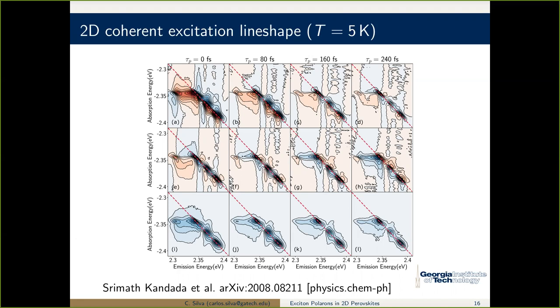It's excitation-induced dephasing. You've got excitons that feel each other coulombically, and that induces the dephasing. It's not that they have to get up to each other and bump, it's that these Coulomb correlations lead to the dephasing. We see that from the zero time spectrum of this two-dimensional measurement. And those correlations are distinctly peculiar for the different excitons because the binding to the lattice is peculiar for each of the individual excitons. So the fact that these are exciton polarons not only gives us the spectral structure, but it also defines the dynamics in a way that is very non-trivial. And that is something that we also must understand in order to understand dynamics in these systems.